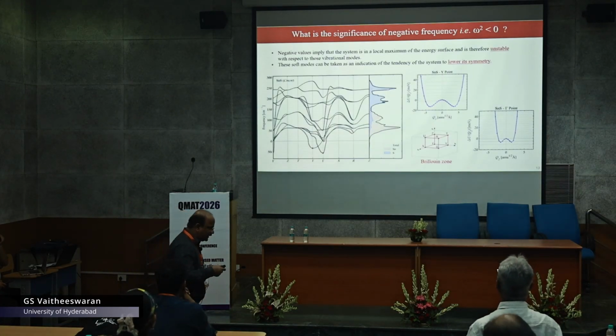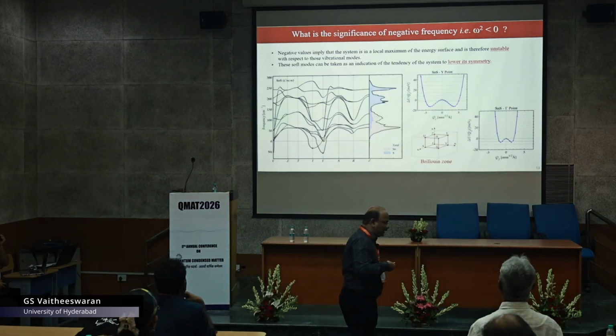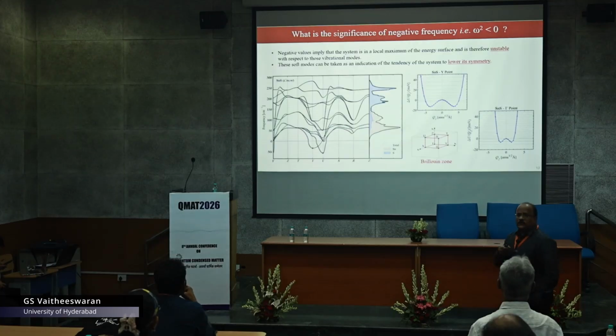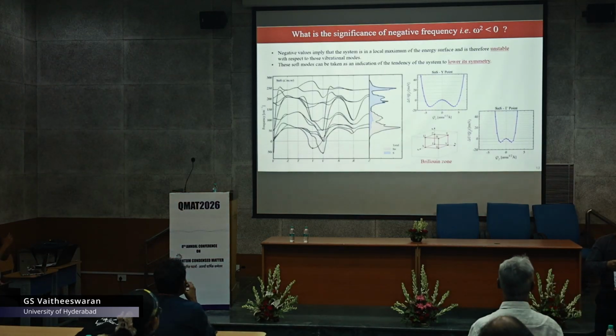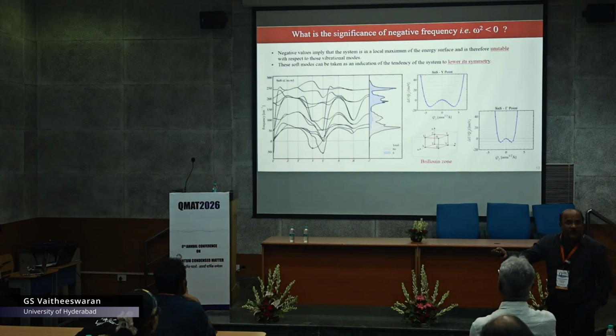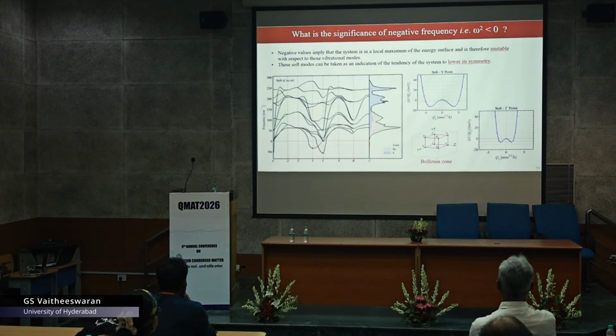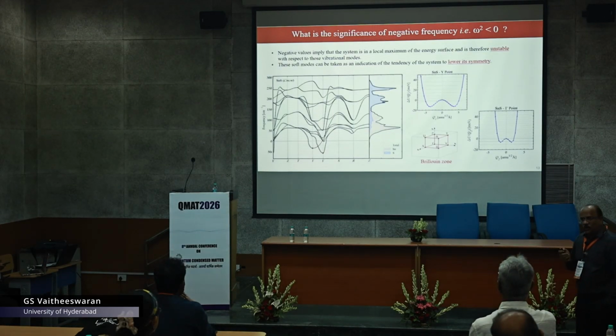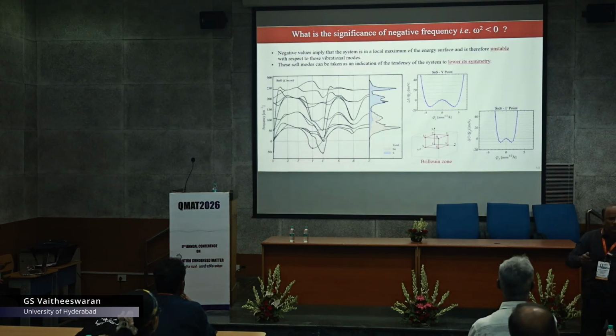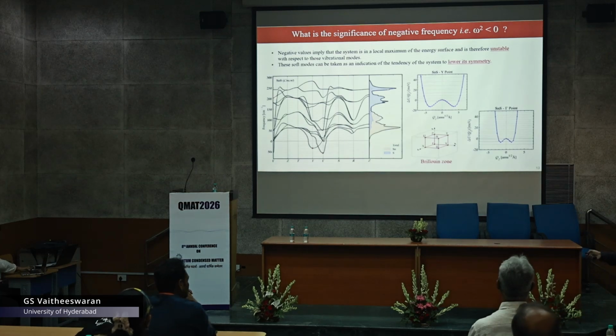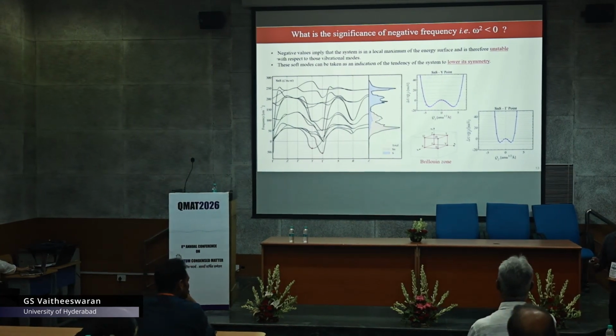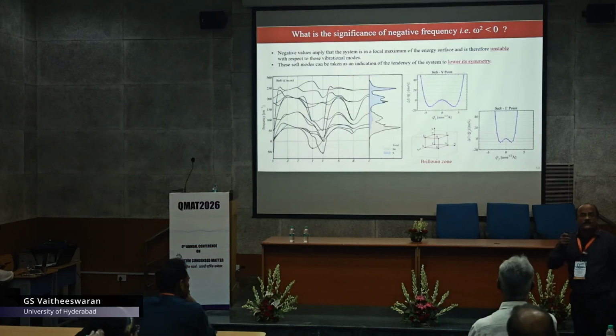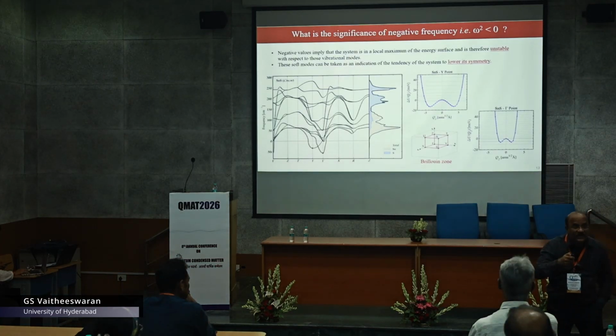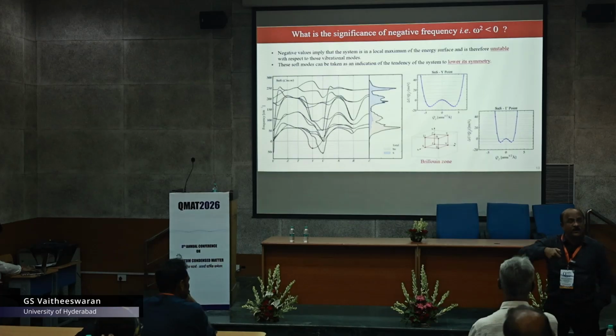Yes, so then there is an interesting thing. We always try to understand the electronic structure and also the phonons. For students, especially when you see some soft modes or imaginary phonon modes in solids, what is the significance of that? Can we rule out the structure as not of use, or how do we proceed further? A classic example is tin sulfide with CMCM orthorhombic symmetry, in which, when you do phonon calculations within the harmonic approximation, you see two kinds of imaginary phonon modes, one at the gamma point and one at the Y point. Eventually there is some interesting physics hidden in this, and one can freeze that particular phonon mode and try to get information about the structural transformation associated with it.